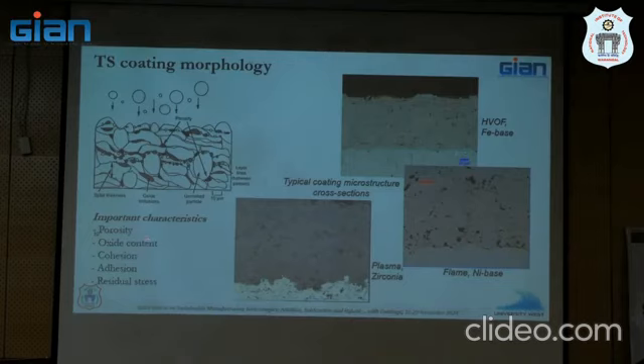Sometimes you get oxides. When you are spraying oxide materials, that's not a problem. But when you are spraying metallic materials, because of the high heat input, some oxidation can take place. And your application then decides whether a certain level of oxide content in the coating is acceptable or not acceptable. Right? But oxide content is another important characteristic.